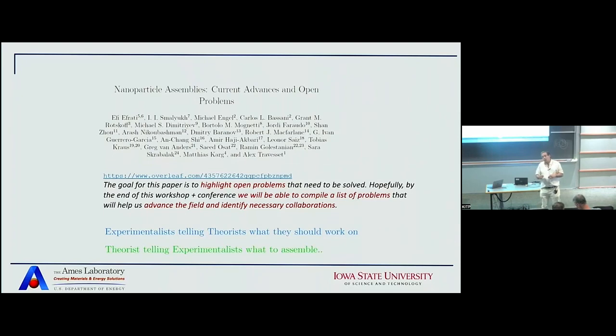Yeah. So there is nothing magic about six. It's just that the effect becomes more drastic the lower the coordination, and six is a reasonable cutoff. But there is no reason why you should. You could add these little corrections, but our goal with this is to predict the lattice constant within 2-3 angstroms, usually less than 3 angstroms. Below that, it doesn't really matter. If you want more, you have to do a simulation and do it very well.